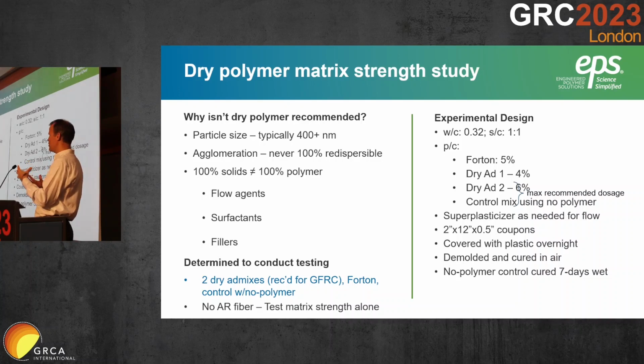Agglomeration: when you make a latex, you spray it into the air, the water evaporates, and these things agglomerate into larger particles. Those are never 100% redispersible. Some of them get really close and disperse very well. Others don't disperse very well at all. But you never get 100% redispersion. So you start off with this many actual particles, and if they're in agglomerates, you just got a large ball of polymer instead